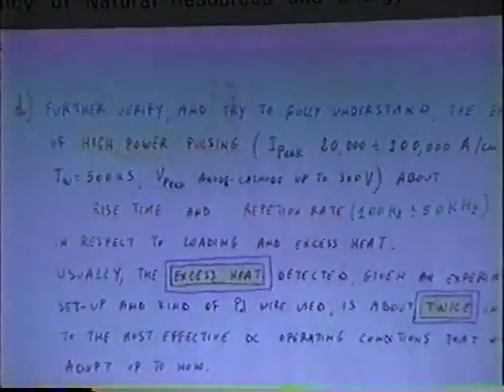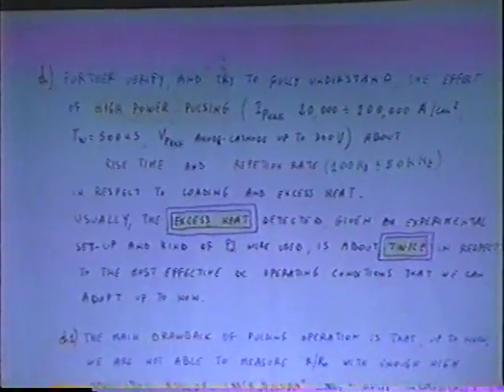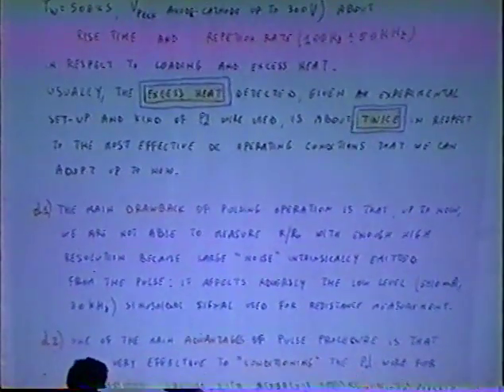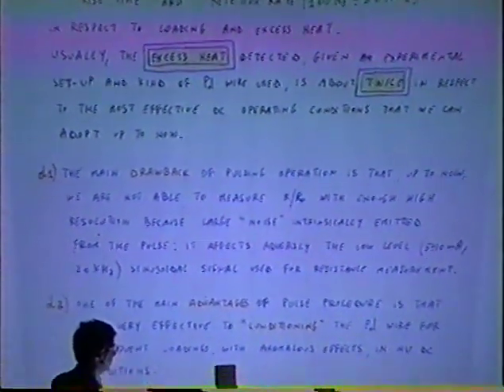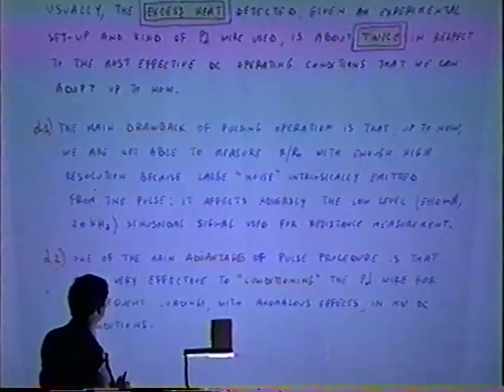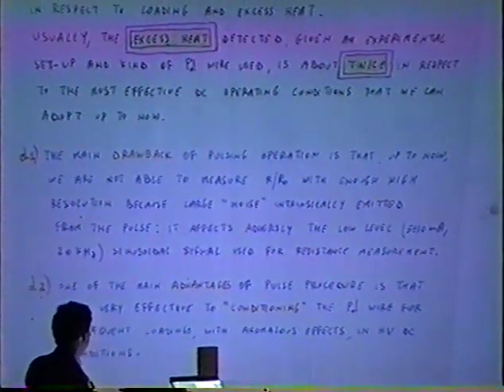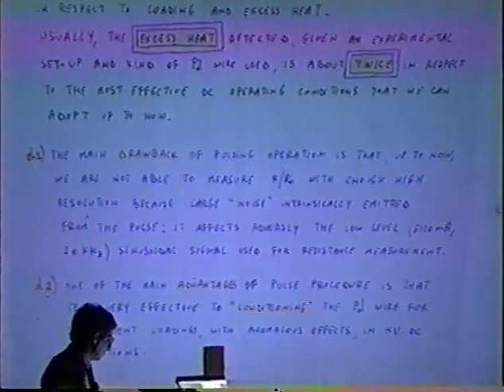Moreover, we want to understand why the pulse condition is very effective to increase loading and moreover the excess heat, the limiting parameters, and why the rest time is so important. Typically, using pulse condition, we get excess heat roughly twice that we can get in the best condition using this electrolysis. The drawback of pulse condition is that it is almost impossible to have high accuracy resistance measurement, because noise is induced from the pulse.